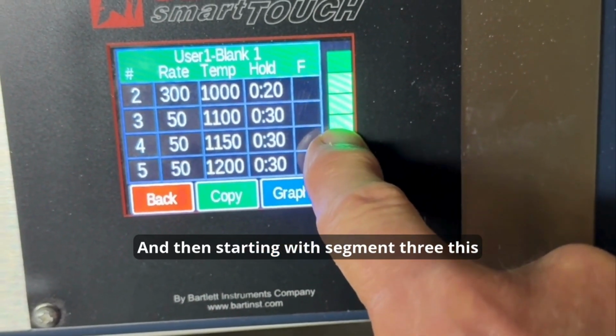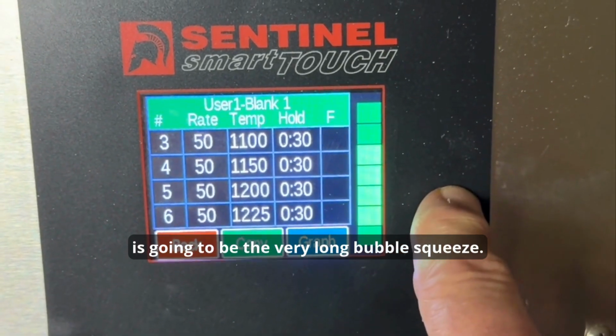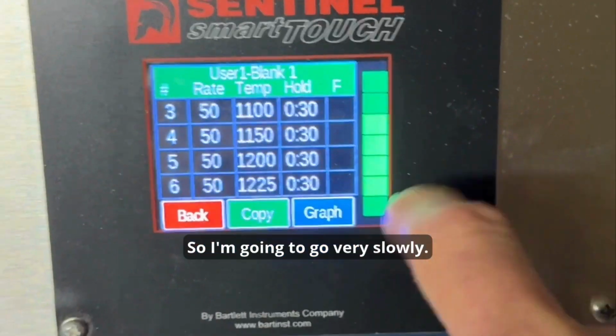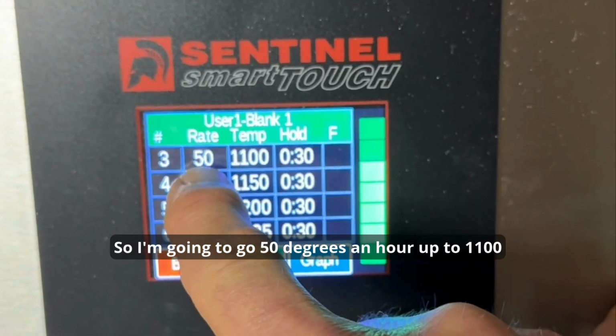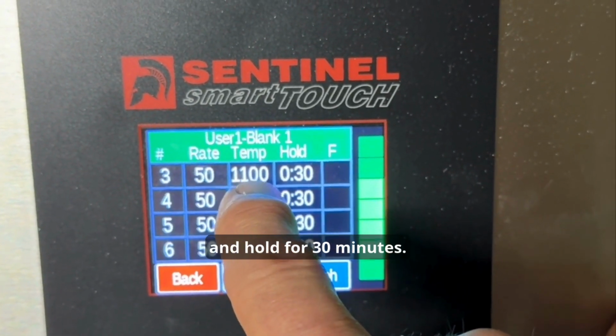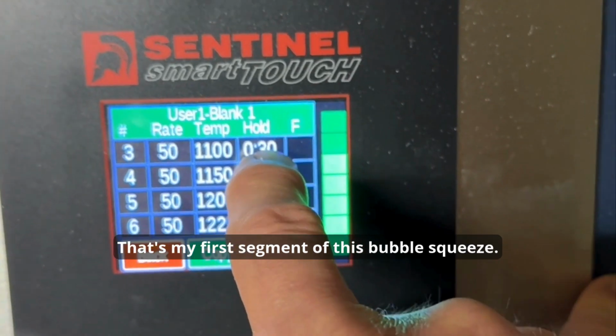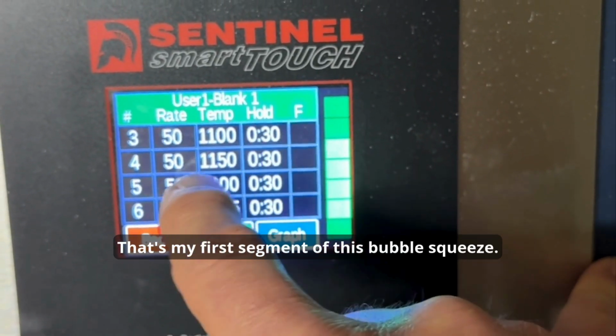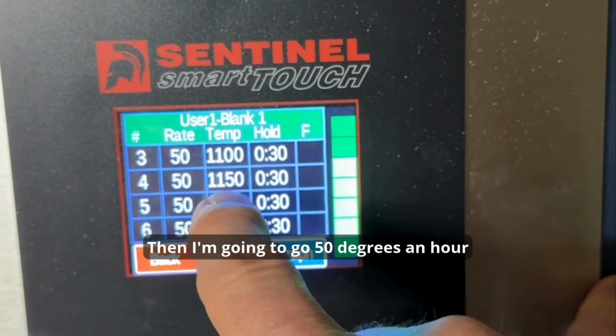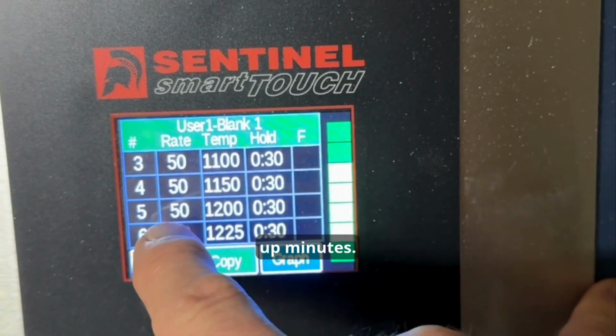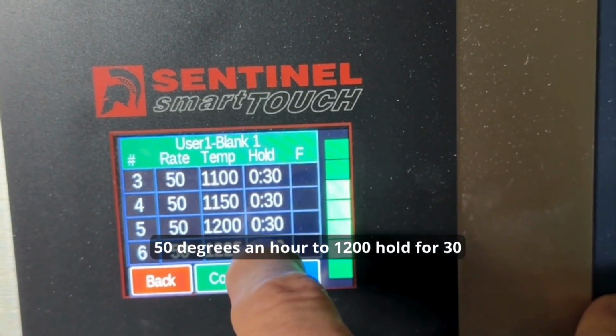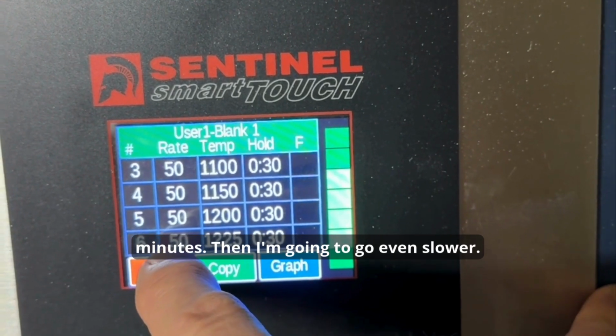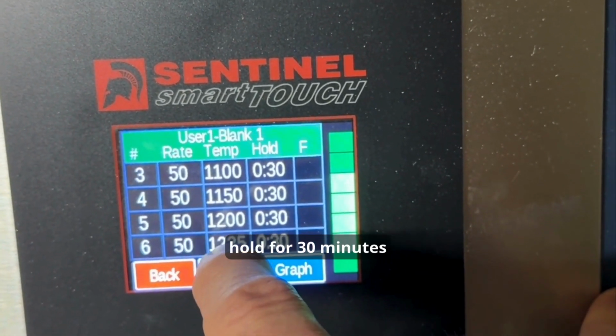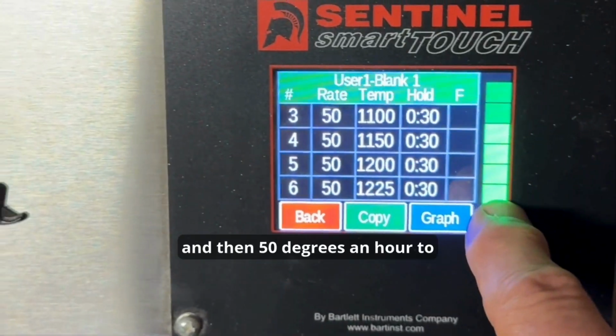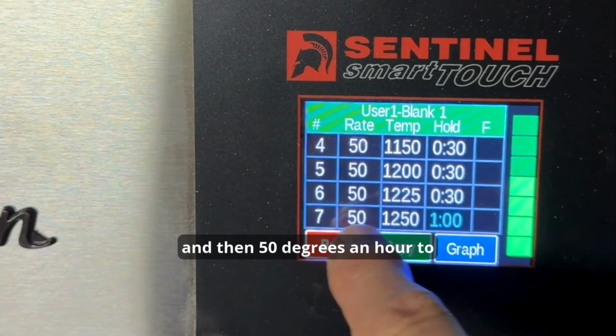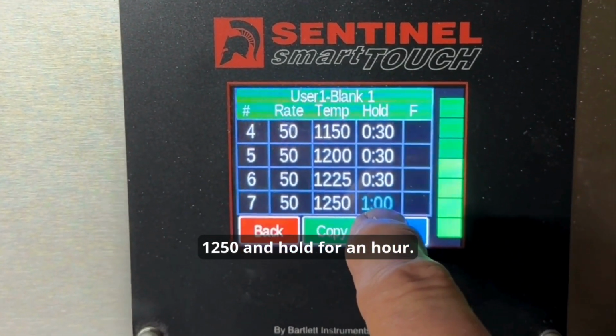And then starting with segment 3, this is going to be the very long bubble squeeze. So I'm going to go very slowly. I'm going to go 50 degrees an hour up to 1100 and hold for 30 minutes. That's my first segment of this bubble squeeze. Then I'm going to go 50 degrees an hour to 1150, hold for 30 minutes. 50 degrees an hour to 1200, hold for 30 minutes. Then I'm going to go even slower. 50 degrees an hour up to 1225, hold for 30 minutes. And then 50 degrees an hour to 1250 and hold for an hour.